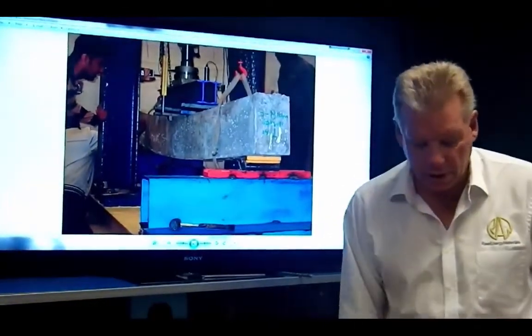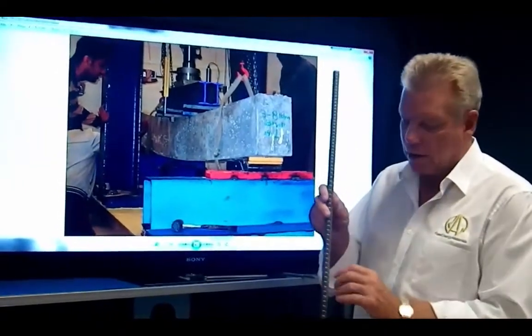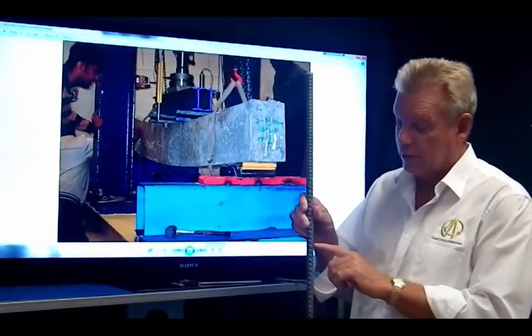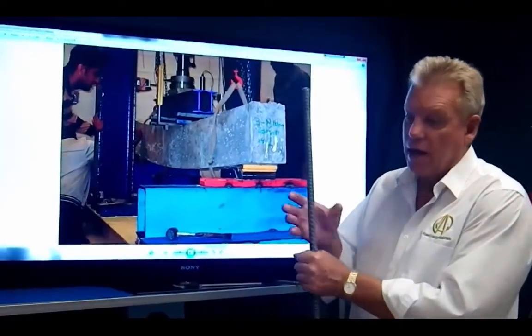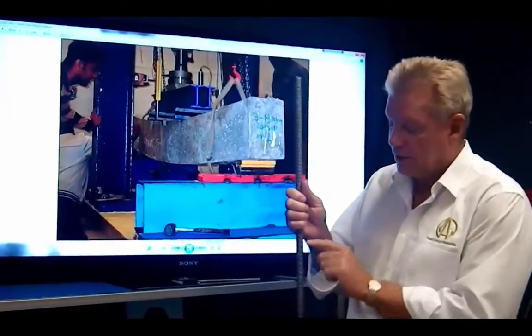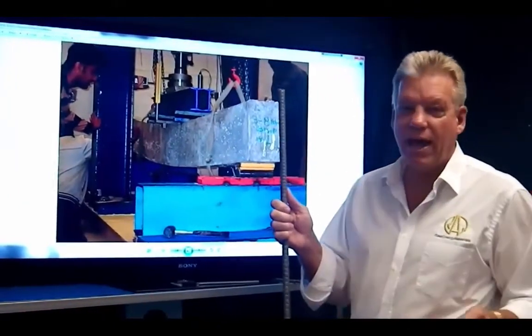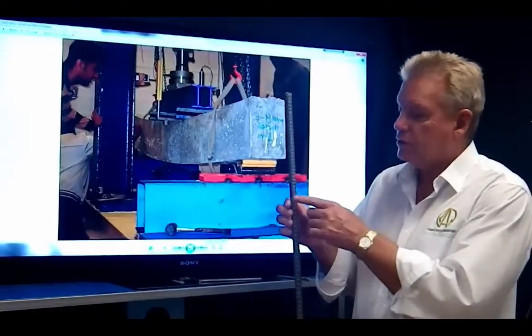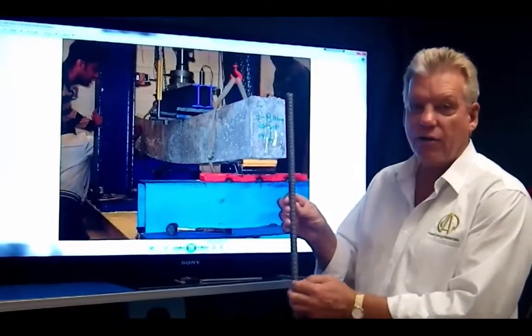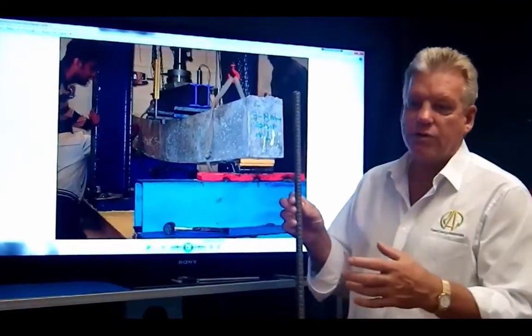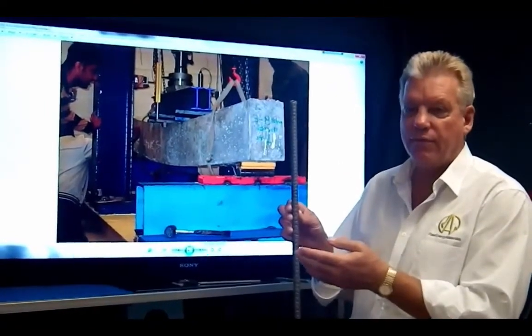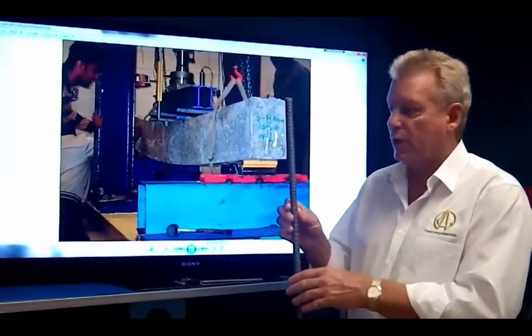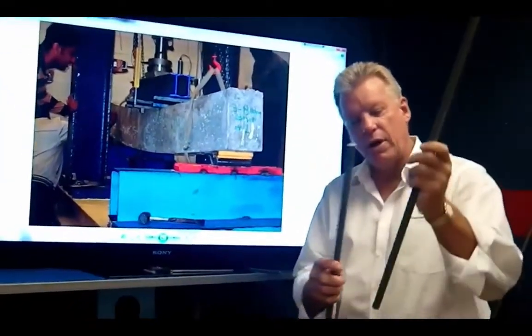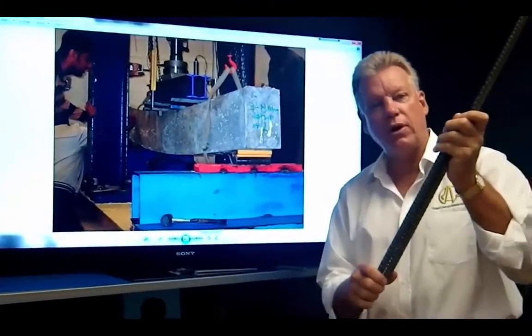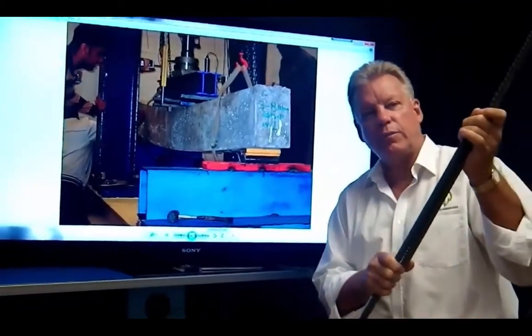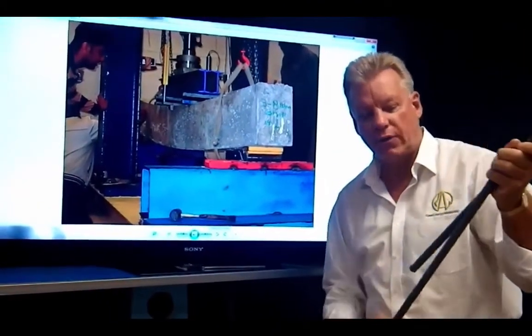We designed rock rebar with a Dacron, or actually we use fiberglass so that we can see it real easy, to squeeze down on the basalt fibers and epoxy as it's made to cause shape changes. The winding doesn't really have anything to do with the strength of the bar, but what it does do is force these shape changes and allow concrete to get in here and get a grip on it. And we have it worked out with the spacing and the depth of these to where we get a really good bond strength. If you're going to overlap two pieces of rock rebar, you want to do it about 20 diameters of the bar, and you're going to achieve in concrete sufficient pull-out to lap from one to the other.